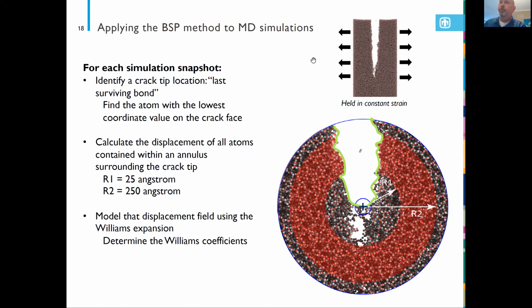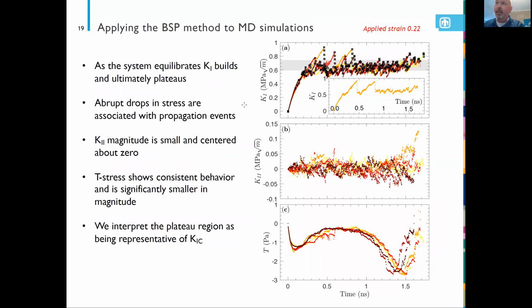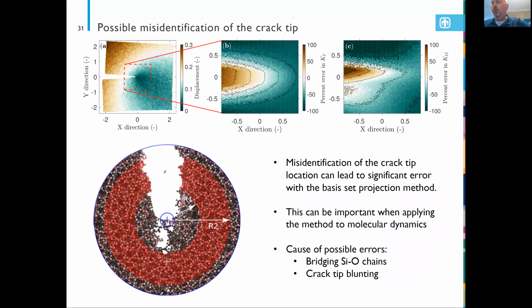How do you resolve this? Because inherently there's no brittle sharp crack when you go to that length scale, it looks like, from your simulations. Oh, you're absolutely right. The blunting of a crack is a challenge, and let me jump forward and share a slide here. One of the issues is that all of the methodology is based upon correctly identifying that crack tip. What you see here is that my typical analysis gives rise to this location, but with the low density, you might find that it's actually deeper within the bulk. And if you misidentify that crack tip, which I've done here and plotted the percent error, the error significantly goes up.